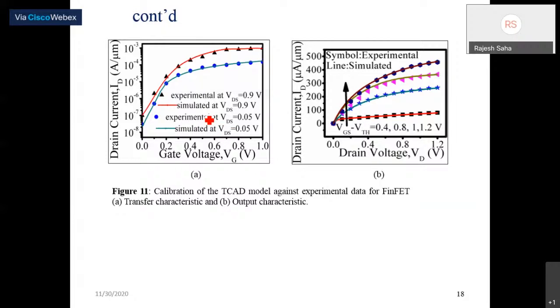Then we have adjusted various parameters in the TCAD simulator, like the mobility parameter and the doping dependence mobility parameter. We have also adjusted the work function of the gate material in order to match the experimental result with the simulator. It is observed that both the transfer as well as the output characteristics show better matching with the experimental data. Here the symbols represent experimental and the line represents simulation. A better agreement is observed between experimental and simulated data. The experimentally calibrated physics models are what we have used for the rest of the simulation, so that we can say our result is validated up to a certain extent.